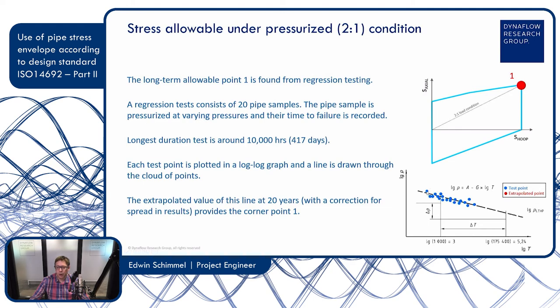With higher pressures, a shorter time to failure. Here, this point is vice versa. And when we have these 20 test points, then we draw a line through it. It's a regression line, and it's kind of an average of all the points that we see here. And if now we extrapolate this line all the way to here, this point corresponds with this number of hours, and that corresponds with 20 years.